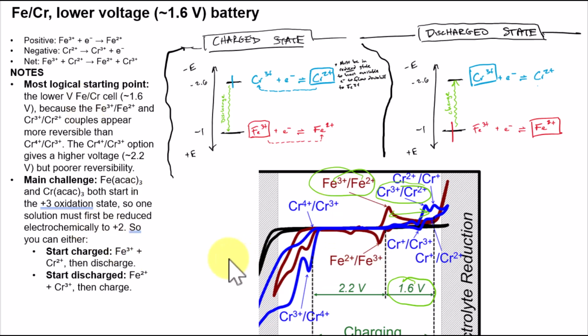The main challenge in this particular cell practically is that the iron 3 ACAC and the chromium 3 ACAC both start in the 3+ oxidation state. In terms of the solid compound, they're both 3+, and so we need one of them to be in the 2+ and the other in 3+, which means you have to do a pre-electrolysis step. You can convert the iron 3+ into 2+ by reducing it coulometrically, or you could do the same for the chromium. But effectively what you have is the charge state. We have the chromium in the 2+ state, so it's highlighted here. There's an electron in this orbital, and because this is a higher energy compound, it's out here at more negative potentials, so this would galvanically descend.